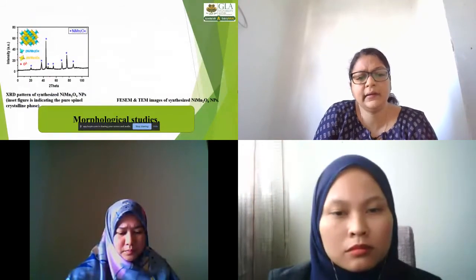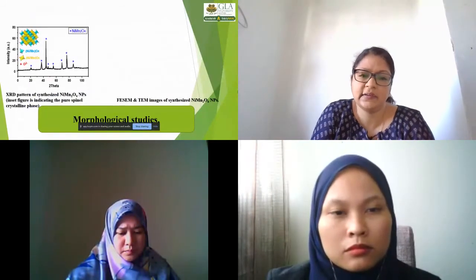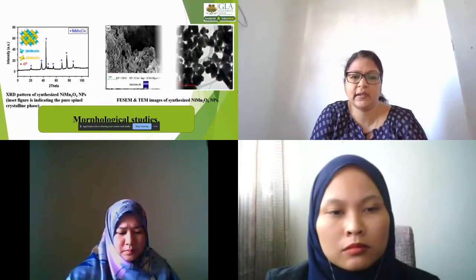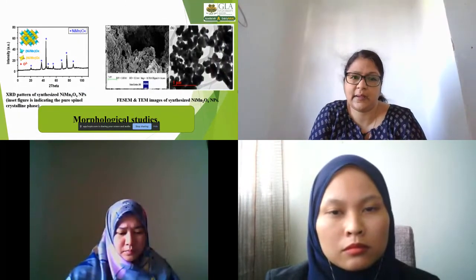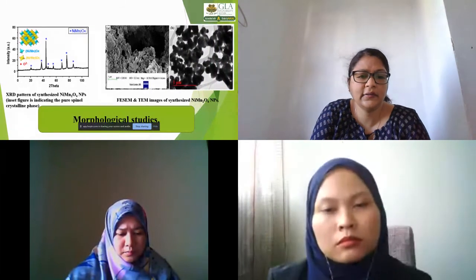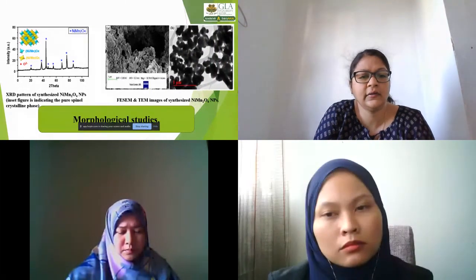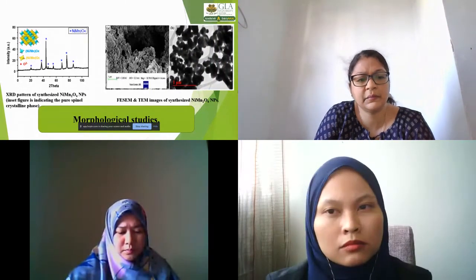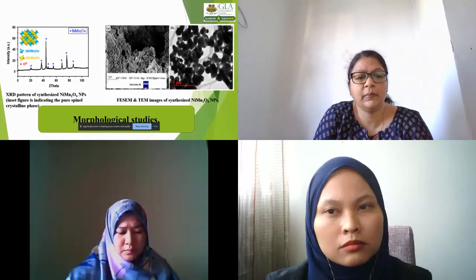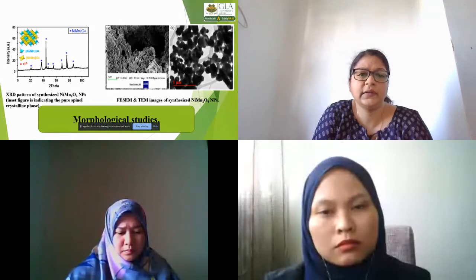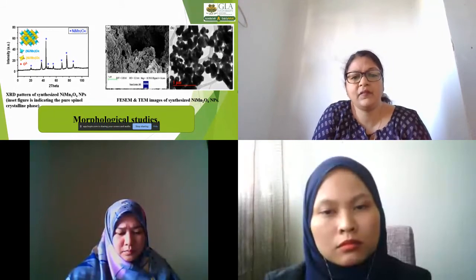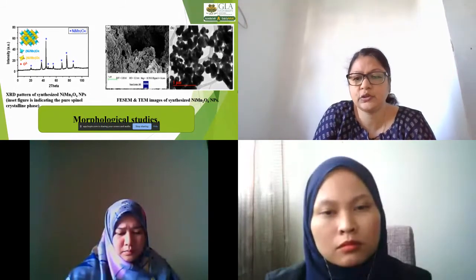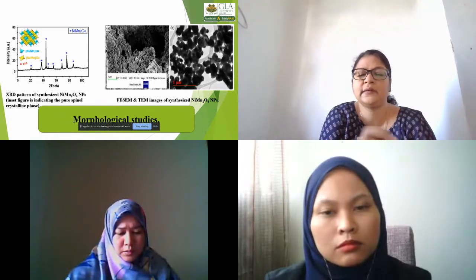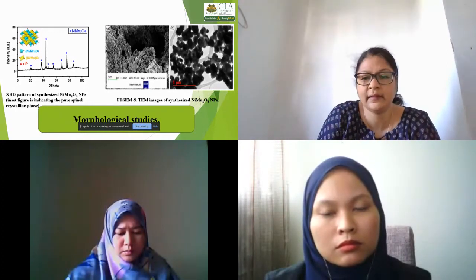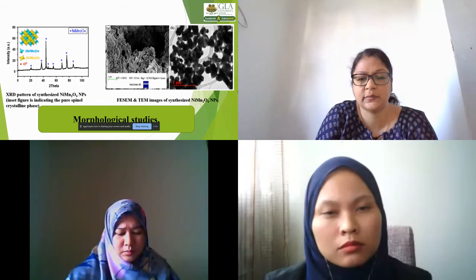We did characterization studies of these nanoparticles using XRD, FESEM, and TEM. XRD results showed us that the crystal structure was a pure phase crystalline structure of the nickel manganate, and FESEM and TEM results showed us the size of the nanoparticles, their morphology, and their size distribution.